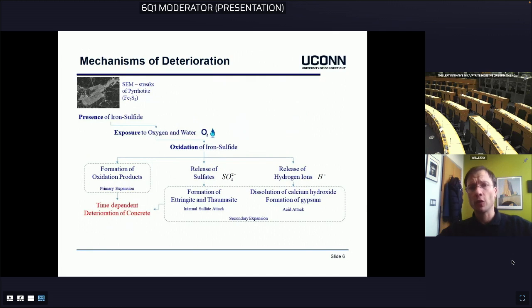So this is a quick overview. You have heard of this already, but the pyrrhotite, for example, the iron sulfide, oxidizes in the presence of oxygen and water, and then it forms those oxidation products, which are primarily expansive, and also releases sulfate, which leads to the secondary formation of minerals, which leads to the secondary expansion. And all of this, and the sulfate attack too with the hydrogen ions, but all of this is time dependent, and then over time leads to the deterioration of concrete.